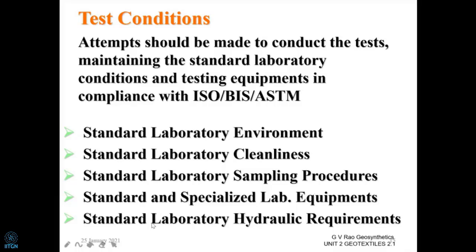And then, of course, we also need specialized hydraulic requirements now. What do you mean hydraulic requirements now? After all, when the flow is going to be so much higher compared to soil in a nano-geotextile, the flow is going to be so high, we need to see that there are no air bubbles in that. We need to maintain the temperature appropriately. And that means we need conditioned water basically. So we need a special system of supplying proper water and a large quantity of water, because the transmissivity and permeability are so high that we need large quantities of water coming very fast. And how to collect it and all is an issue, which we'll see as we keep going.